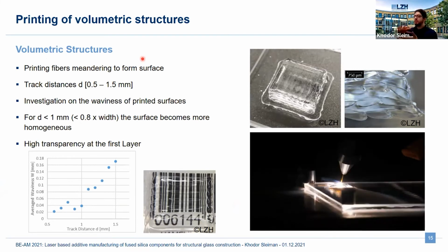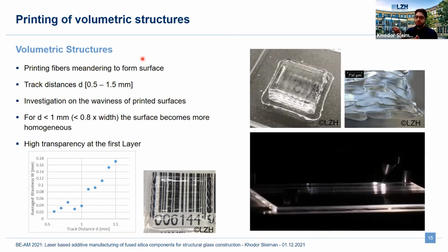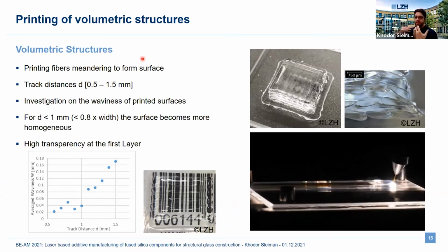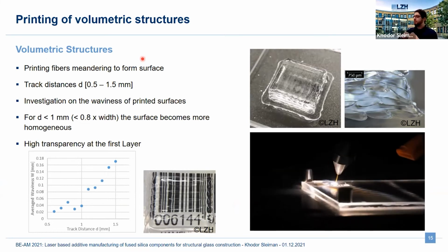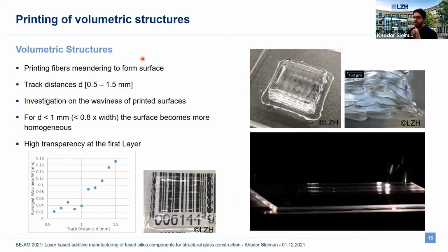And we investigated the average waviness of the surface to see what kind of track distances are used to form a homogeneous surface. And we found out that a track distance of 80% of the original track width is quite suitable to form a low waviness of the surface. In the top view of one layer, you can see that it's quite transparent, but for multiple layers, there are gaining counts of bubbles.